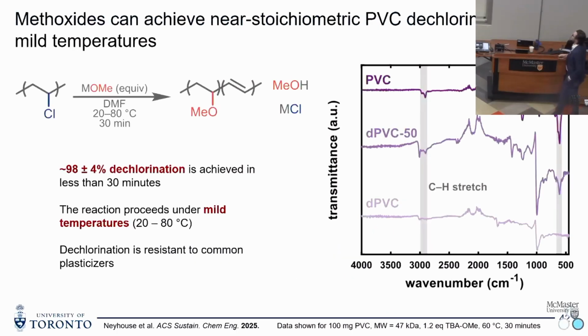So we apply that. The only thing I want to highlight here is that this reaction, again, runs under fairly mild conditions. The benefit of using an organic base like this is that it is a very potent base. Most alkoxides readily dechlorinate PVC at very mild temperatures. We can do this at room temperature. Heating it up a little bit speeds up the reaction and gets us to higher dechlorination efficiencies. And we get pretty representative structures that tell us we're removing chlorine from the polymer.